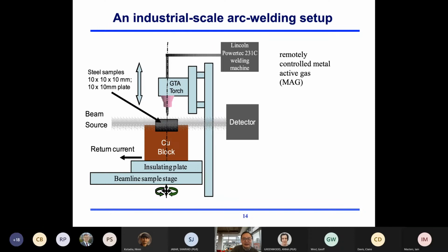So in our experiments, we did this kind of design. It's quite simple. This is our arc gun, and the beam source comes through this way, and this is the detector, essentially a transmission detector. And we try to cool down a copper block. In the initial design, we wanted to rotate the sample, but in the end we gave up because the dynamics in the weld pool are much faster than the rotating speed you can achieve.